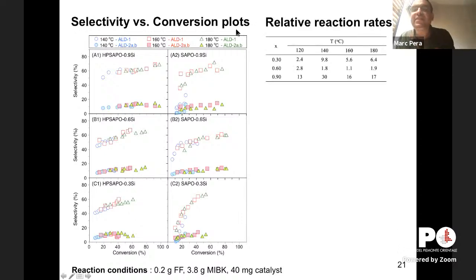So here I'm plotting in this table, I'm just comparing the initial reaction rate. We just measure the TOF, the turnover frequency for the different catalysts, for hierarchical and not hierarchical. So the bigger this number is, the more reaction rate you have compared to the microporous material. You see that for 0.9, the difference in rates is spectacular. We can even have values at 30 times faster with a hierarchical material compared to a non-hierarchical material.